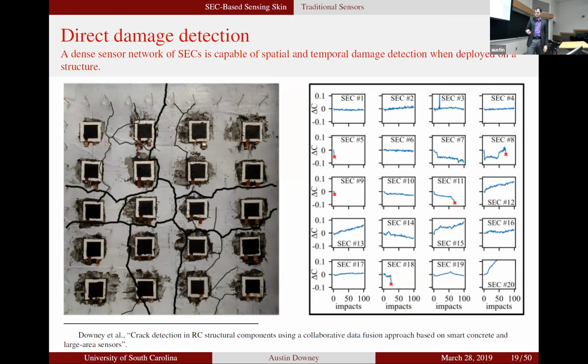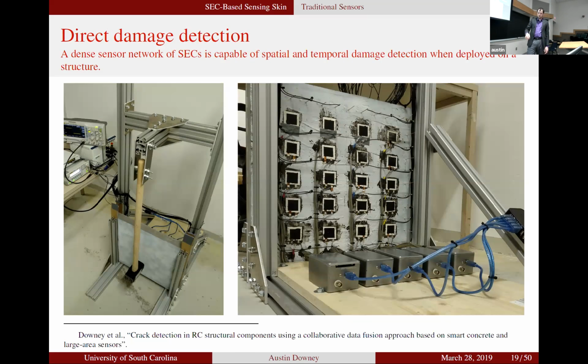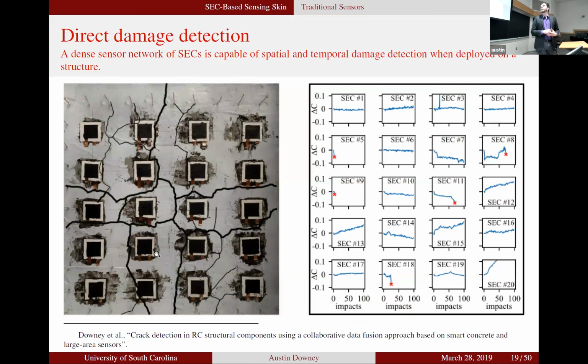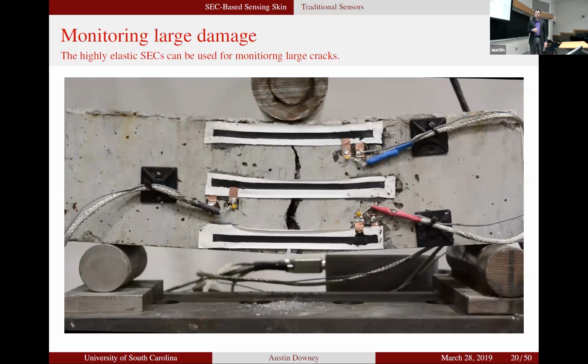And when we impact it with the hammer, so this hammer on the front just kind of repetitively falls into the concrete plate, anytime that a crack goes through an SEC, we're able to detect it quite clearly. However, when we have cracks that form around SECs, which you can see happens quite readily here, we have more challenges. And this would have to be solved through a model-based approach, right? Looking at actual strain maps. But the other interesting thing is we can make these SECs in any shape we want, and they're incredibly elastic.